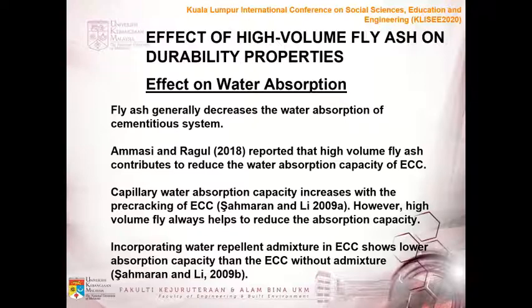Capillary water absorption capacity, which is also known as sorptivity, increases with the pre-cracking of ECC, reported by Sahmaran and Li. However, high volume fly ash always helps to reduce the absorption capacity. Later, they also reported that incorporating water repellent admixture in ECC shows lower absorption capacity than ECC without admixture.